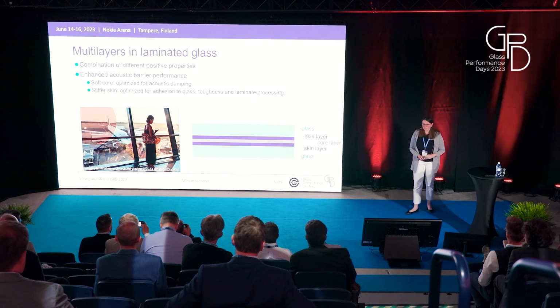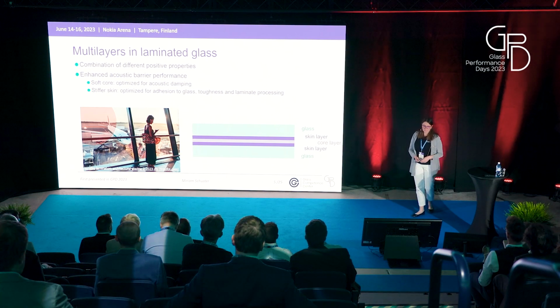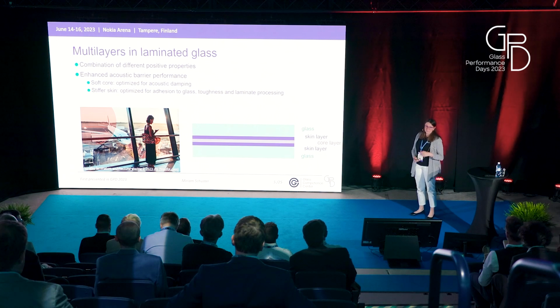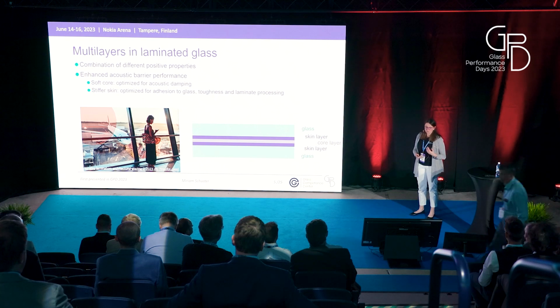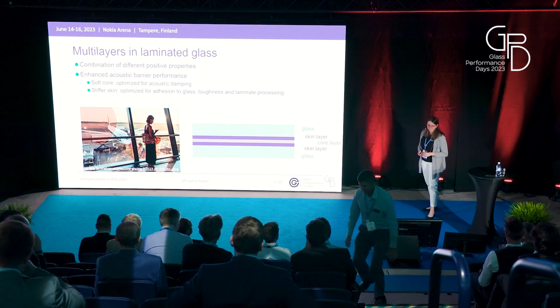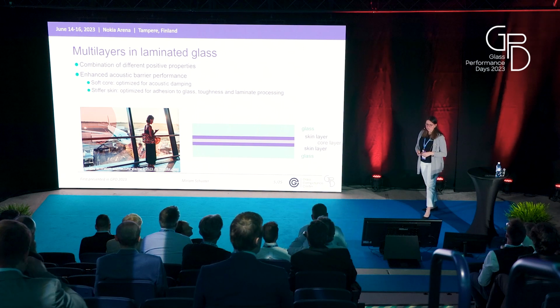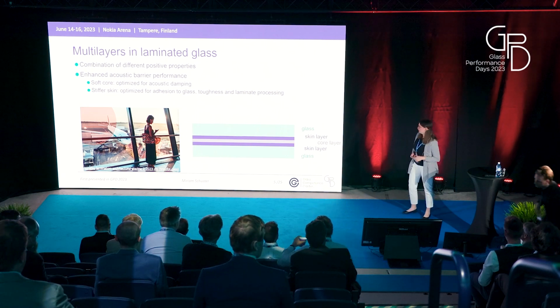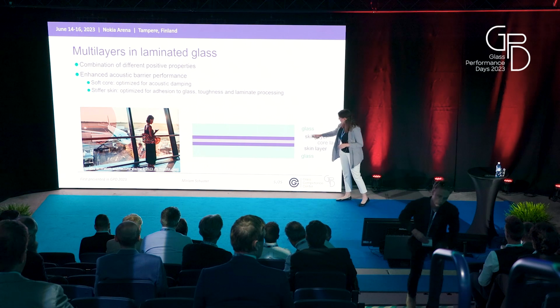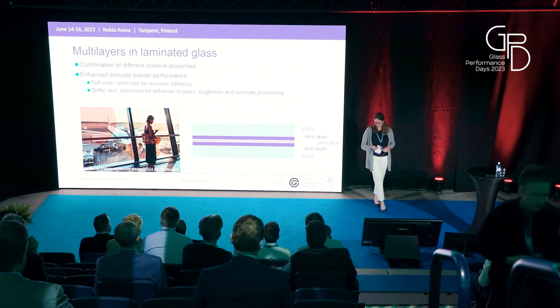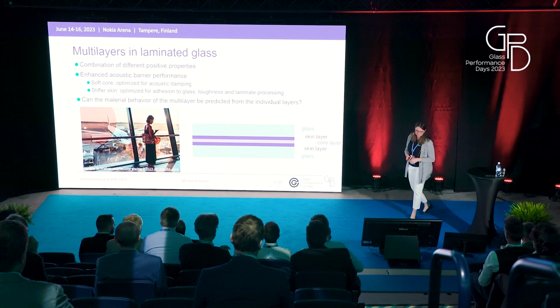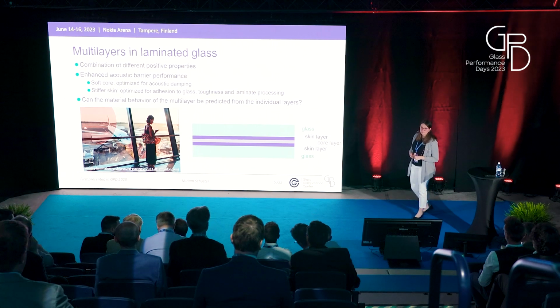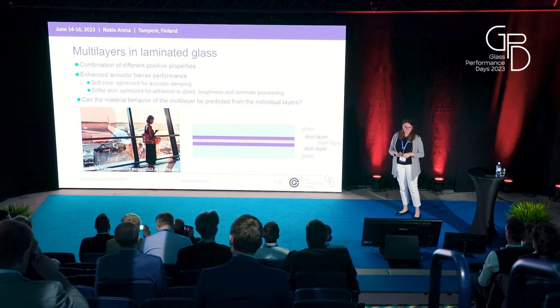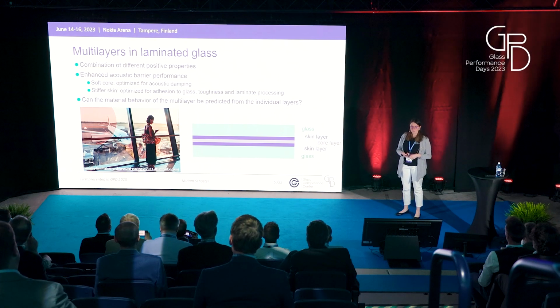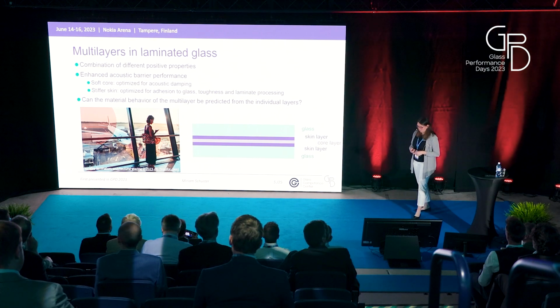However, soft interlayers are more complicated to process, and hence stiffer layers are used and put around the softer core layer in order to enhance the laminate processing. And in total, we have then a three-layer, which is shown in this scheme. So we have two skin layers and in the middle a core layer. And now the big question is, can the material behavior of this three-layer be predicted from the material behavior of the individual layers?